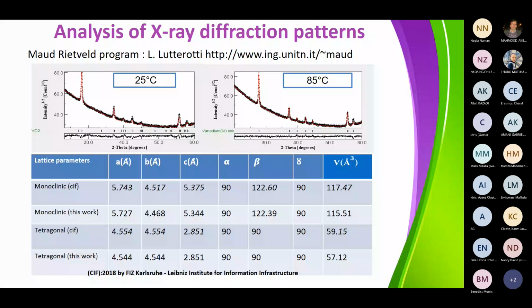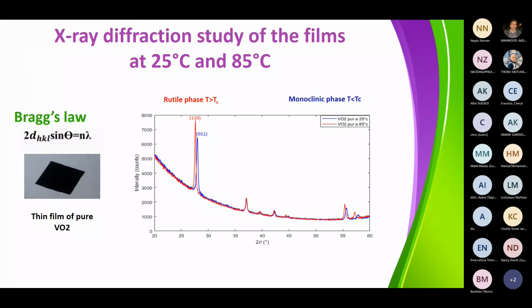Additionally, once you have done that, you can look at how you go from the 011 monoclinic reflection to the 110 rutile reflection. So you measure this as a function of temperature, and you look at how this 011 reflection is shifting towards the 110 reflection of the rutile phase.